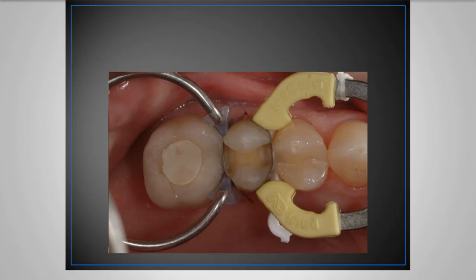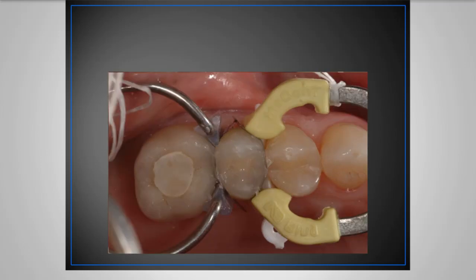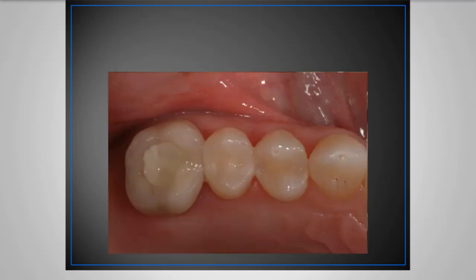And on the pulpal area, since we're not close to it, we're only a couple millimeters down on the pulpal area. We're not close where I'm not concerned about it as much. Now, had the pulpal floor been as deep as the proximal boxes, I would probably use a different technique as my first increment. Now, if something were deeper than 4 millimeters, I would place something else down first, and then have no problem or hesitation to place this bulk fill material, the Voco x-tra fil, on top of it. So again, here's what it looks like afterwards. Great looking restoration with one increment.